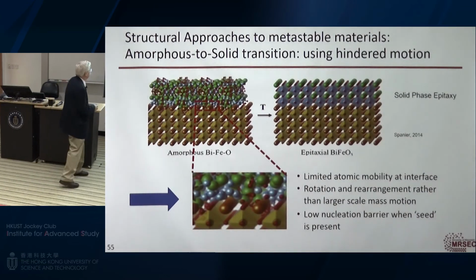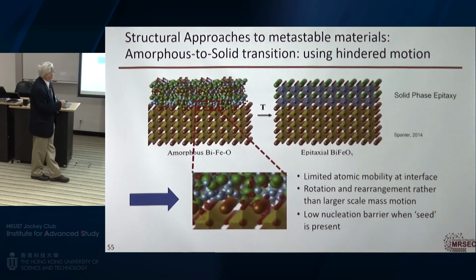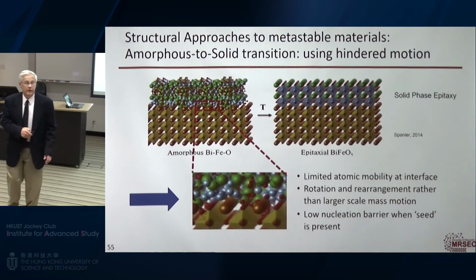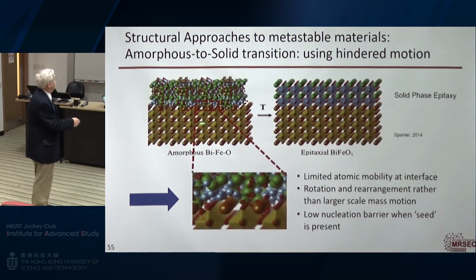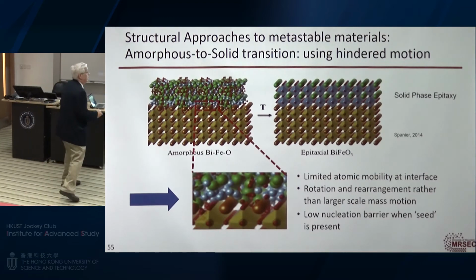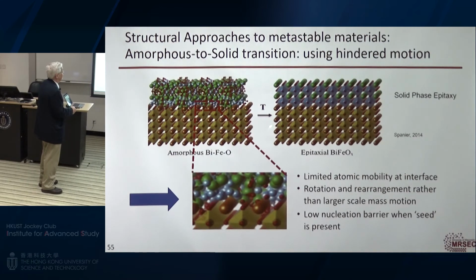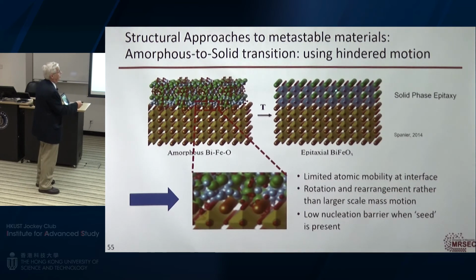The other approach that we've used to make a metastable material is based on oxides, and this is something that we're working on now. It uses the idea that if I take an oxide, or a material, and here's my substrate, and I put down an amorphous material, I can put down any composition I want, as long as it's amorphous, because I deposit atoms at a very low temperature. And if I heat it up, what we hope would happen is that the material will reorder at the interface and start to develop epitaxial order.